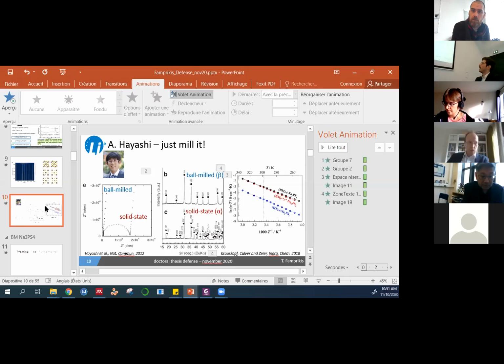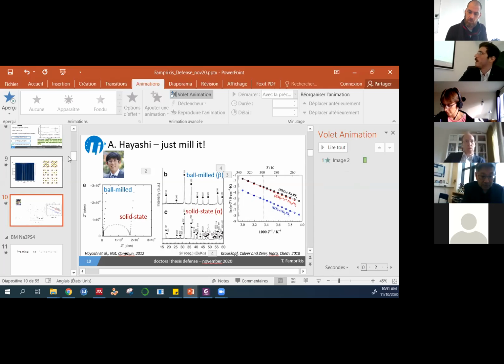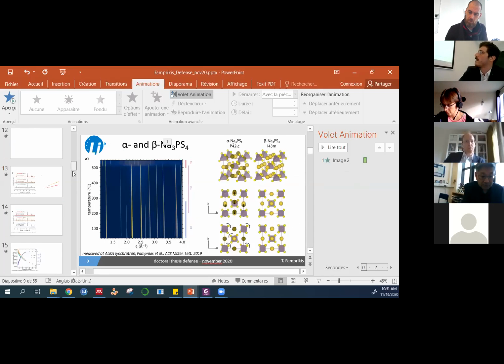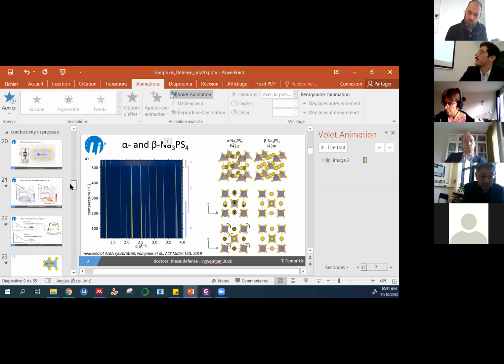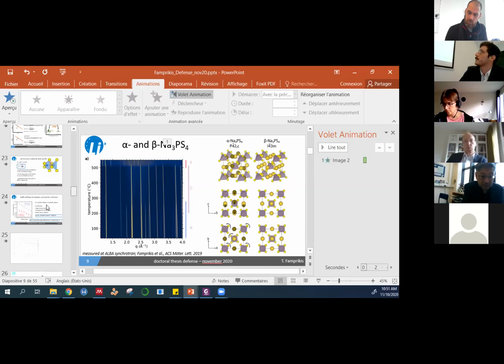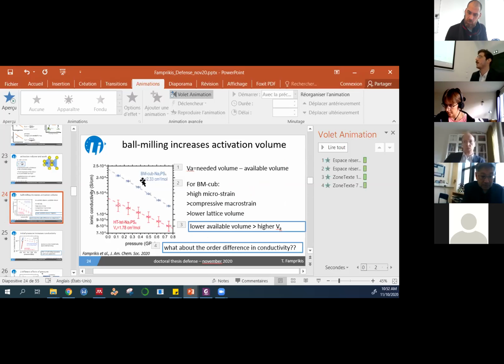Okay. But what I should say is that, first of all, we see from the results that I showed that you can actually get the mechanochemically synthesized and solid state synthesized material to conduct very closely by applying pressure. But you are right that, even if we look at my results here, in the end the ball mill sample still has the edge, still conducts, let's say, 2 times better, right?